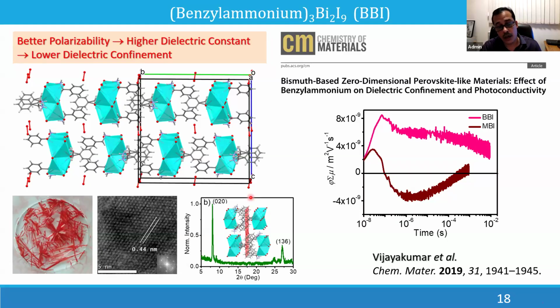Okay, the organic component is actually playing a key role, unlike in other cases. Till 2019, the researchers were using methyl ammonium kind of small units. There they are actually inert components, and they don't participate in the structural aspect of the material. Okay, here we were able to bring a role for the organic component, not only the polarizability and reducing the dielectric confinement, but it also directs the structural properties of this material, because it actually pulled the growth in that packing direction. That is why we were able to get a significant peak in the 0 2 0 reflection. Okay, that actually corresponds to the growth, or the packing, of the organic component.